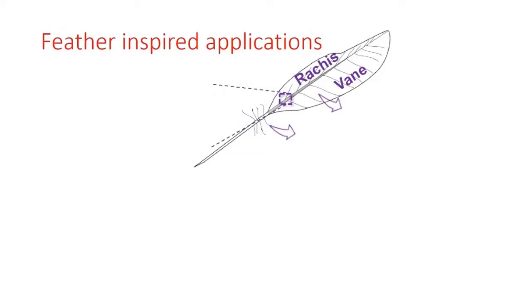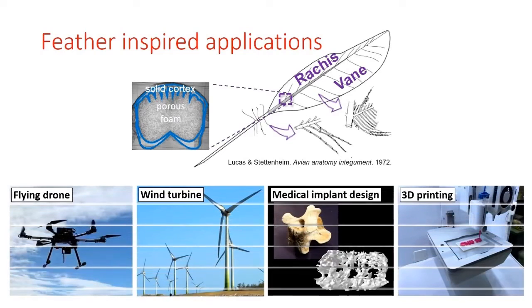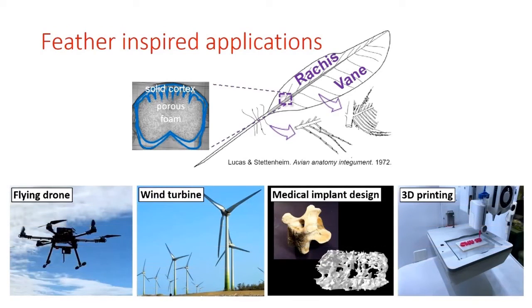At the application level, our multidisciplinary approach is capable of resolving various details of cellular compositions in tissues. The cortex medulla composition with different organizations of cellular origami makes the rachis a shaft with tunable material properties. The vane is made of fractal-like paper cutting principles with highly effective branch interweave. These modules enhance the functional flexibility of a flight feather. The architecture principles we have learned from nature in this study may inspire the development of novel composite materials and promote the advance of additive manufacturing technologies.